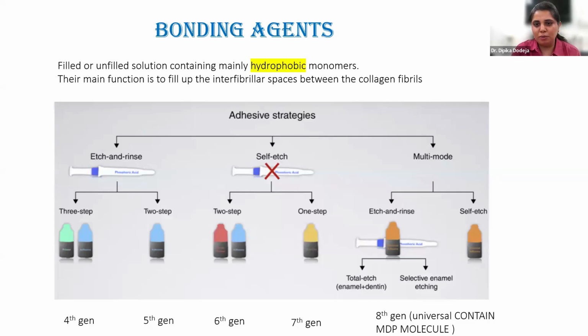Why an eighth generation? These are called universal bonds. Why? Because they contain MDP. Now, what does an MDP monomer do? Instead of relying on the resin tags, the phosphate part of the MDP molecule binds to the calcium from the hydroxyapatite. The salt that is formed with the calcium of the hydroxyapatite is relatively less water soluble. Also, they can bond to various other substrates like zirconia and alumina.